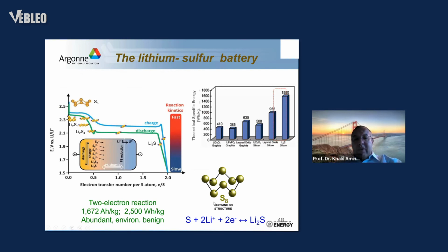Here is the sulfur. It's a 2-electron transfer. It has an average voltage of 2 volt, with multiple steps because of dissolution of polysulfide. As you can see from here, the overall gravimetric energy is very high, 2,500 watt-hour per kg. It is very abundant, environmentally benign, and the cost is basically dirt cheap. 1 ton of sulfur is about $110.